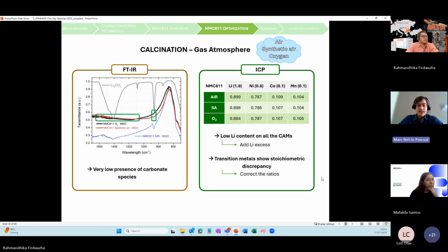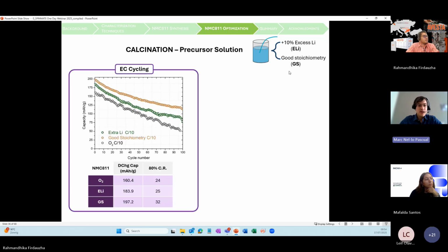So if you move to the next slide, the last thing that we checked was these two different samples. One where we added 10% excess lithium in the precursor solution, and also a second sample with this 10% excess lithium, but where we also corrected the stoichiometry to be on the 8:1:1 ratio. And the electrochemical performance for these materials was much better. In the case of the excess lithium material, we see a discharge capacity around 180 and 25 cycles of capacity retention. And for the good stoichiometry, we got close to 200 milliampere hours per gram and 32 cycles. So now we are on the right performance of this kind of materials.